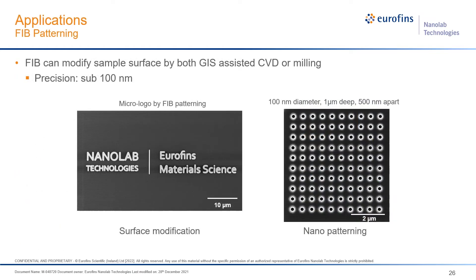Other than milling cross-sections, FIB can also perform nano-patterning or surface modification by both deposition and milling with accuracy down to sub-100 nanometers. Here is a micro-logo of NanoLab fabricated using FIB milling. On the right-hand side, a 10 by 10 nano-array with 100-nanometer diameter holes, 1 micron deep, and 500 nanometers apart was created using the milling method.